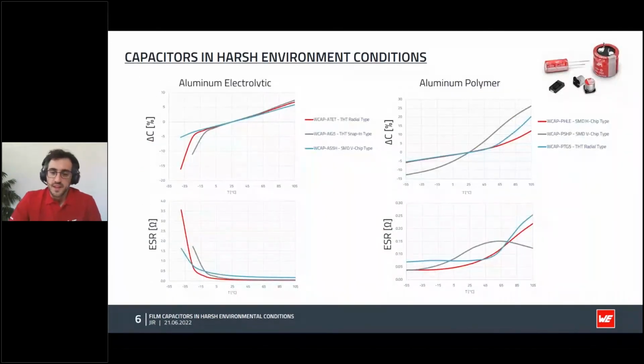On the right side, similar measurements with aluminum polymer capacitors. The V-chip SMD types have a very different construction. That is the reason for the very different characteristics. As you can see, polymer capacitors will work perfectly fine at very low temperatures. At high temperatures, the performance may be much worse because of the increase in ESR. But the components will handle the exposure to high temperature much better because the solid electrolyte will not dry.